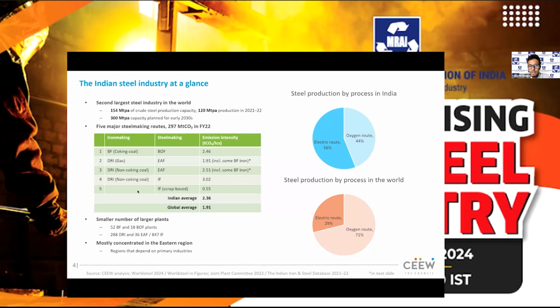You have the BF-BOF process, which, as I mentioned, uses iron ore and coking coal. You have the gas-based DRI and EAF. You have the coal-based DRI with the EAF. And then you have the coal-based DRI with the induction furnace as well, called the IF. And then you have induction furnaces that purely melt scrap steel and produce recycled steels from scrap.